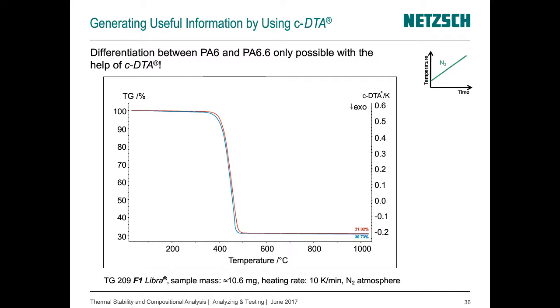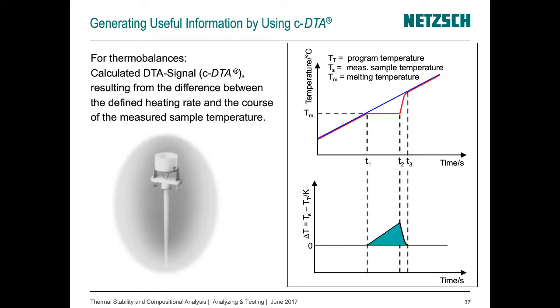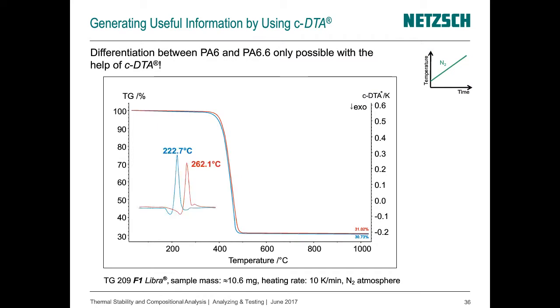Nobody knows. But here we have also a possibility to get some further information, and this further information is CDTA, which stands for Calculated DTA Signal, and this means that the sample thermocouple must be in close contact to the sample crucible to feel any temperature change inside of the sample. And then it's possible to calculate such a CDTA signal for getting more information. If we do this in our case, then we get two peaks. A blue one with a peak temperature of 223 degrees C, and a red one with a peak temperature of 262 degrees C. And now we can separate them.